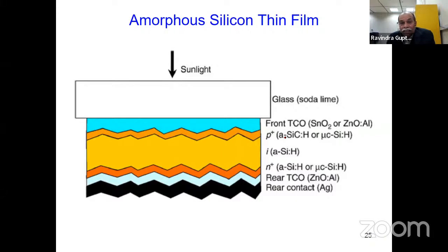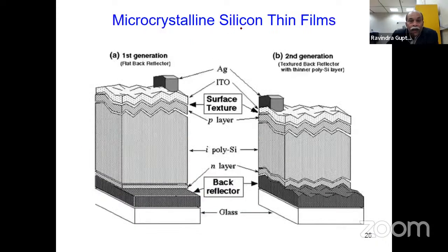You can see here, this is the amorphous silicon carbide or hydrogenated microcrystalline silicon. And then we have intrinsic amorphous silicon here. And then we have N highly doped amorphous silicon, or the microcrystalline silicon. And then we have the rear TCO. Then we have back contact, which is made of silver, or nowadays we are using aluminum. So this is the basic configuration for the amorphous silicon-based thin film. And this is the microcrystalline silicon-based thin films. Here, this is the glass.